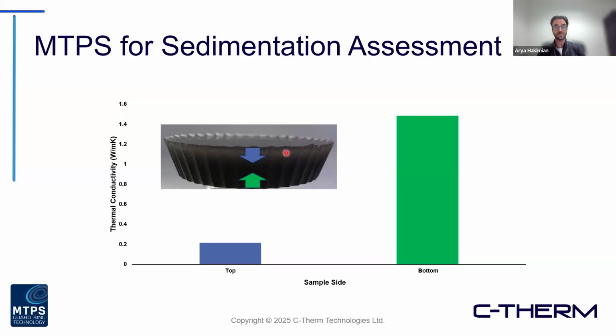And how we can actually pick up on this is with the MTPS, again, single-sided, the depth to which we're measuring is a few millimeters into your sample. So by taking your sample coupon and placing, let's say, side A in contact and taking a measurement, and then flipping it and doing the other side, we can compare those results. Ideally, they would be exactly the same, indicating consistency throughout. Or if you're seeing something like this, where, let's say, the top side is significantly lower than the bottom, we can infer that all of that, or a lot of that, conductive filler has settled towards one side. So again, it's finding ways to utilize these different methods to demonstrate some property of your material, whether this is for R&D, QA, QC applications. There's quite a bit of relevance here in terms of allowing sample optimization.